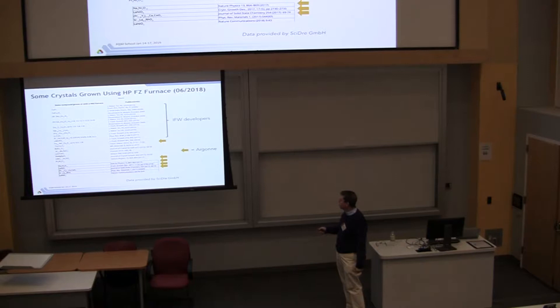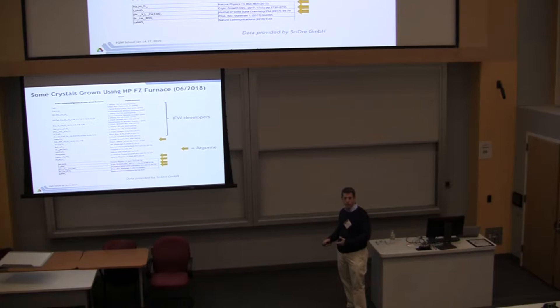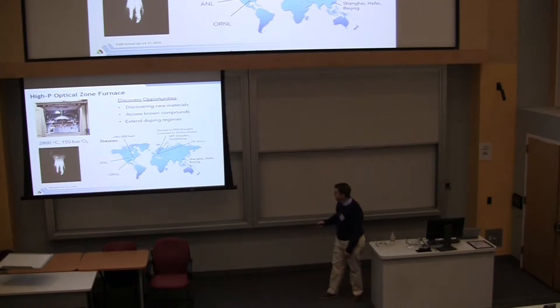So you can adjust the composition of that atmosphere or, as you'll see, the pressure. So it's containerless. You don't have contamination from a crucible or a transport agent. We can control the atmosphere. That's the main theme of this talk. And you can grow crystals that are either congruently melting or incongruently melting. So if you think about crystal growth, you guys know the difference. You can grow an incongruently melting compound.